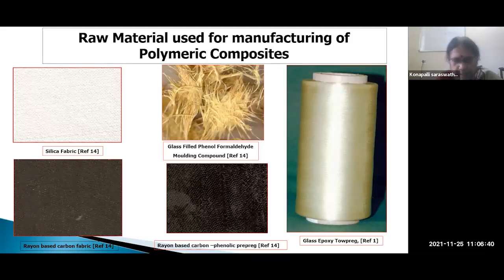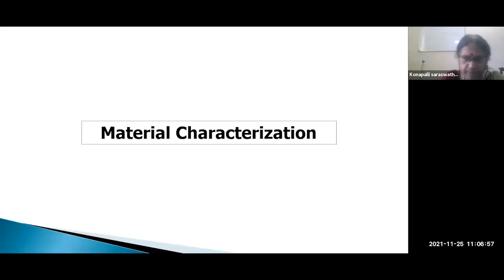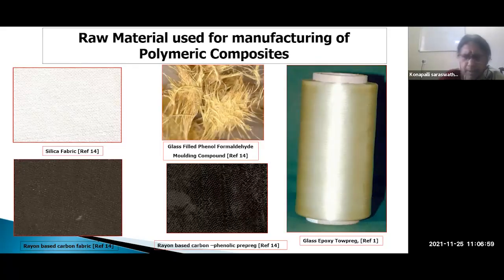And we use phenolic resin. This is the rayon carbon fabric phenolic prepreg. And this is a glass filled phenol formaldehyde molding powder. As I told you, a lot of molding processes are there. So already we make the compound, molding compound, which is used for molding of the components. This is the glass tow prepreg.